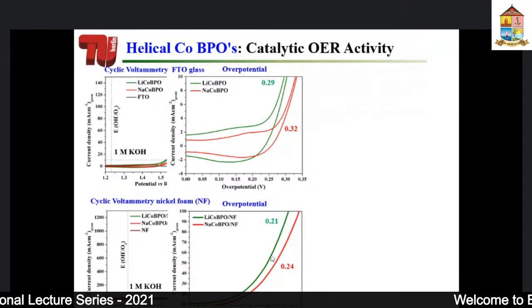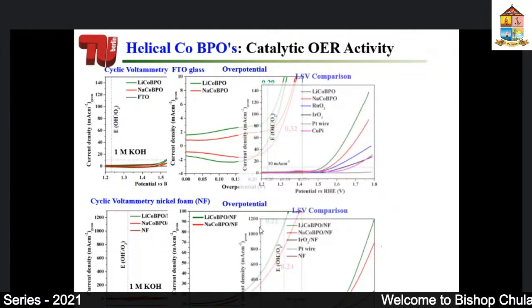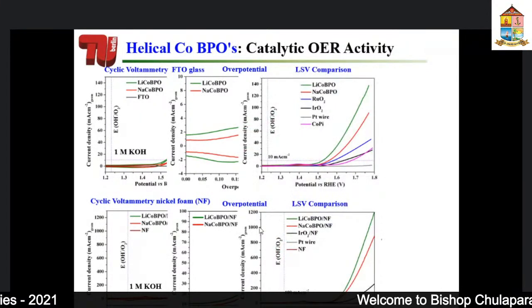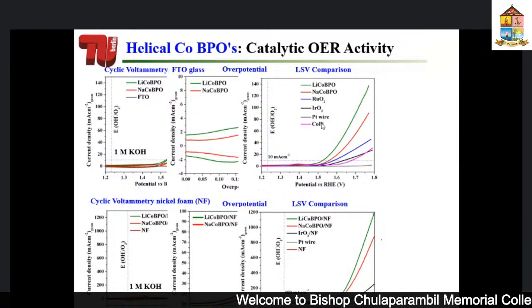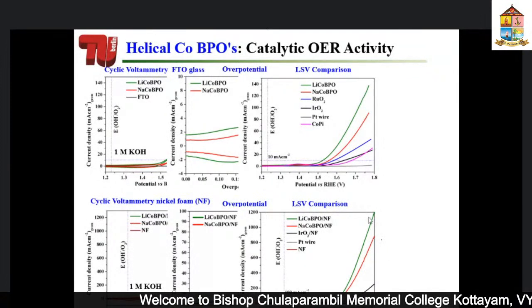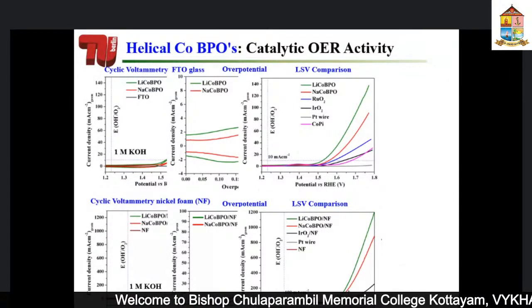On the other hand, we need only 200 millivolt, which is very little compared to other catalysts reported in literature. So we also compared these curves with the reference materials such as iridium and ruthenium, which are supposed to be the best catalysts to drive this reaction. We also tested some other important compounds, and we see that our materials are much more active than all these reported materials. Same situation here, we get much better current and much better overpotentials.